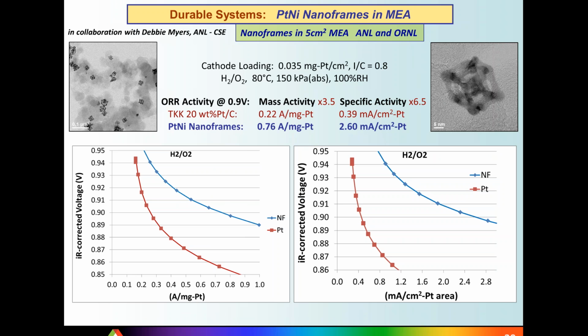And now I would like to show you a few examples of how those advanced catalysts are behaving in MEAs. So MEA is a different environment than RDE. Rotating disk electrode is, again, an ideal electrochemical environment without any impurities. And in MEA, we are looking into surface chemistry, which is much more complex. Plus, we are introducing ionomers. So this is a summary of MEA studies, which was done here at Argonne in collaboration with Debbie Myers. And we employed our platinum nickel nanoframes with multi-layered platinum skin surfaces, and mass activity was improved 3.5 times and specific activity 6.5 times.